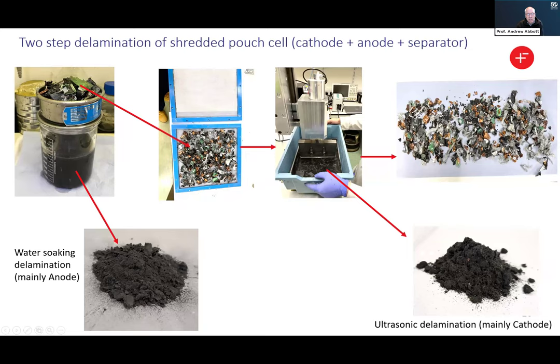We're then taking our material in the blue frame in the middle that you can see. You can see the copper foils to see where the carbon has been delaminated. We're then putting that underneath our ultrasonic horn and ending up with just foils. The plastic separates out through gravity, and we end up with a very pure cathode stream of active material at the end of that process. So we can see that by rethinking and redesigning that process and using new tools in that separation, we can lead to higher value materials much more rapidly than current technology.